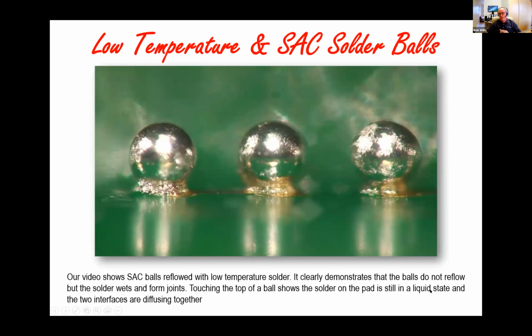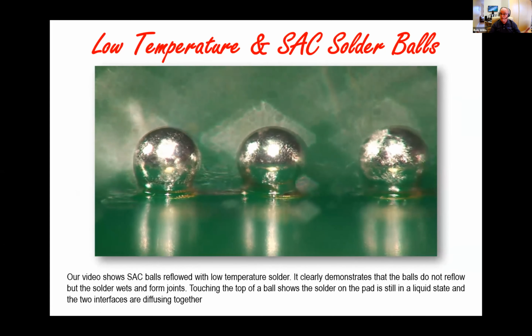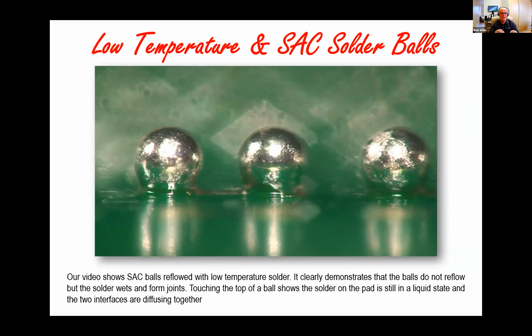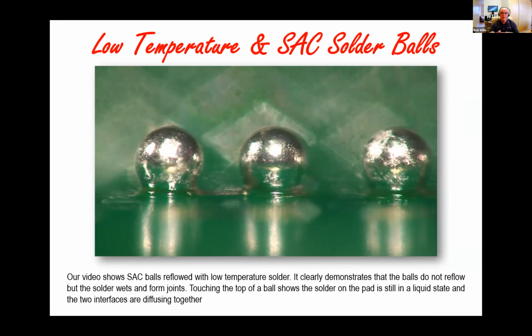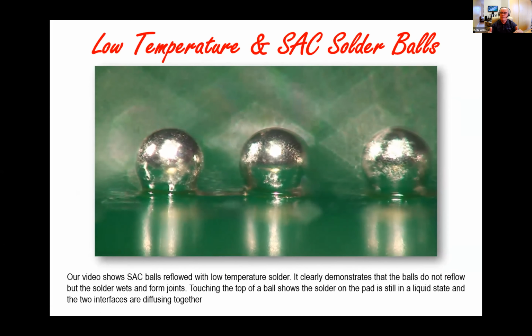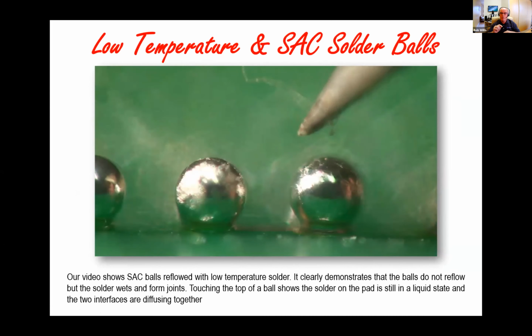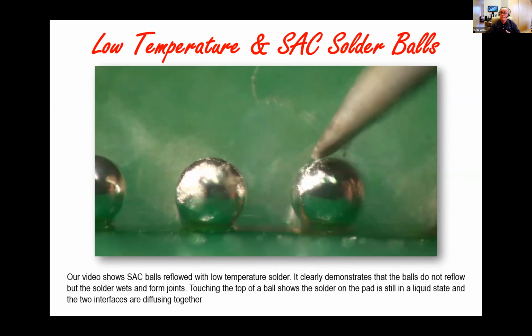this process. If you're not quite understanding as I'm explaining, this is a simple demonstration of low temperature soldering of solder spheres on a BGA package. Well, they're not actually on a package, they're just little balls at the moment. But the point I'm trying to illustrate is we're making reliable interconnection with the pads to the solder spheres. And if I then push one of the spheres, you can see the sphere is not liquid. So we're soldering to the termination. We're not actually reflowing both terminations during the soldering process. It's exactly the same as perhaps Matt in his earlier years soldering with tin lead technology to high temperature balls, high temperature columns. They form a reliable joint, but they don't actually become liquid in their own right.